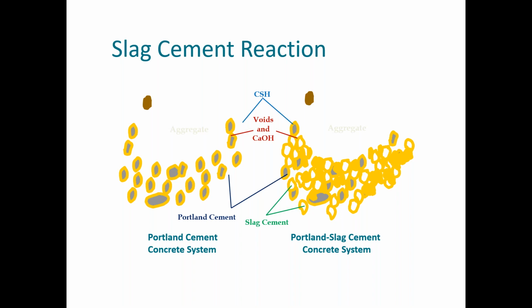No worries. I think it's a wonderful illustration if it was fully colored in, but apparently that didn't make it in the translation. But you can see that light area that says aggregate. Imagine there's an aggregate particle there, and you're looking at two different systems. A system where the paste is comprised of only Portland cement, or at least the powder component is only Portland cement, and then a Portland cement and slag system. These gray particles represent cement particles. The yellow coatings around them represent the reaction product that happens through the hydration process, called calcium silicate hydrate, CSH. Then you end up with these microscopic voids, and in this case they're very large, but I promise you there were more dense.